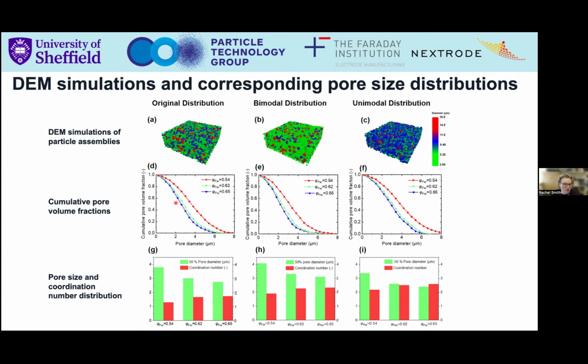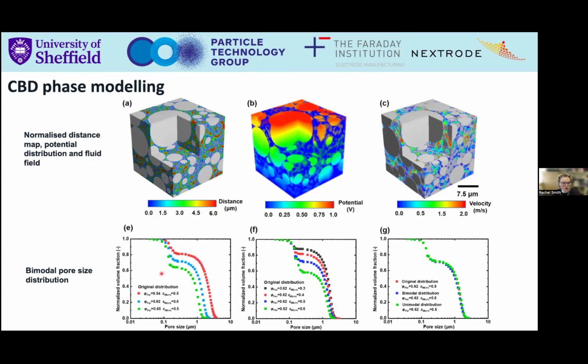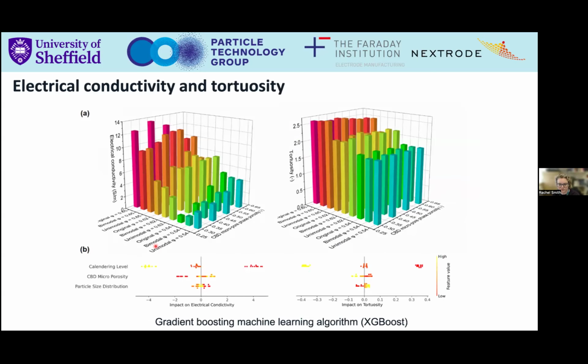We also changed our cumulative pore volume fraction, so basically calendaring to different levels. And we changed our pore size distribution, so we changed the fraction of the pores that are taken up with the micropores as opposed to the macropores. And so we did all these manipulations. And then we also looked at the thickness of the electrode, which is known to have a very strong effect on performance of the electrodes, especially at high C rates, at higher power draw, basically.